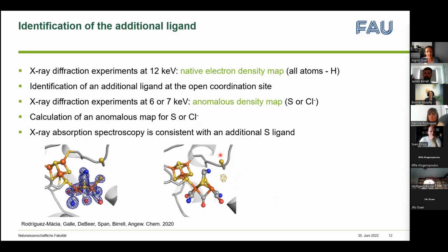Of course, we also see density for the cysteines and the other sulfurs, the bridging sulfurs, so all the sulfurs in the structure, the thiols, cysteines, the 4-iron 4-sulfur cluster. So we see electron density for all these atoms. What is also really nice is that at 7 keV, right below the iron edge, we don't see the electron density of the irons that could sometimes mask this electron density because they're very intense. So 7 keV actually turned out to be the perfect energy for determining the sulfur map.